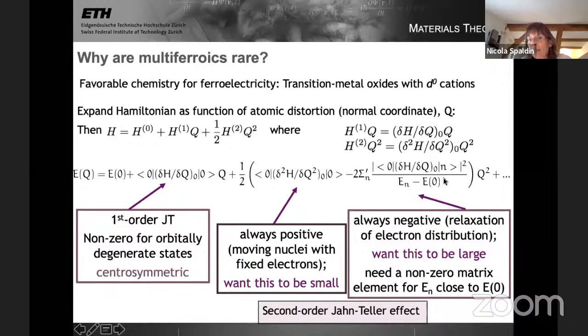And this is the term mathematically describing that rehybridization of the electrons we just looked at in the cartoon. This we want to be large, and because the perturbation is odd symmetry, since we want a polar distortion, we need the ground state and the first excited state to have opposite parity. So we need a non-zero matrix element in the numerator, and the denominator should be fairly small. What this means in particular is, for example, I can't have the ground state and the first excited state composed entirely of d electrons because they have the same parity. So let me show you what happens in a typical ferroelectric, and then I'll stop maybe for questions.